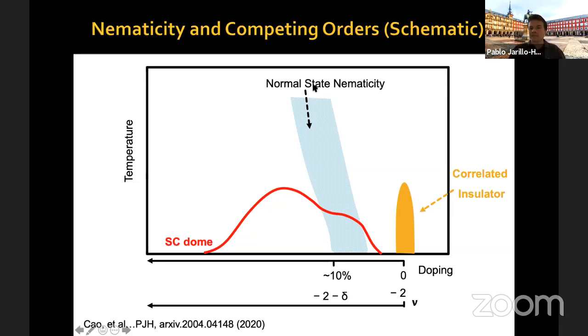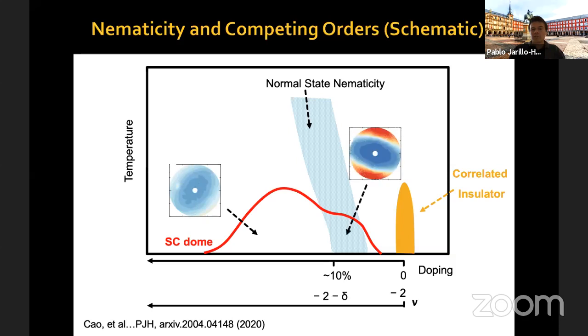We have this resistance wedge at about 10% doping from the correlated insulator state. This resistance wedge exhibits normal state anisotropies consistent with normal state nematicity, which competes with superconductivity, such that in the superconducting dome you have a depletion around that region where the normal state anisotropy is. Okay? Now, in the superconducting state, we measured anisotropy everywhere in the superconducting dome. Okay, we have this nematic superconductivity everywhere in the superconducting dome.